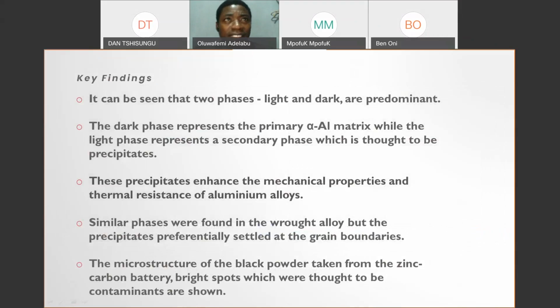Now, based on our findings, it can be seen that there were two phases, the light and the dark, which were predominant. The dark phase represents the primary alpha aluminium matrix, while the light phase represents a secondary phase, which is thought to be precipitate. This precipitate enhances the mechanical properties and thermal resistance of aluminium alloy. Similar phases were found in the wrought alloy, but the precipitate preferentially settled at the grain boundaries. So in the microstructure of the black powder taken from the zinc carbon battery, the bright spot areas were thought to be contaminants, as shown also in the image.